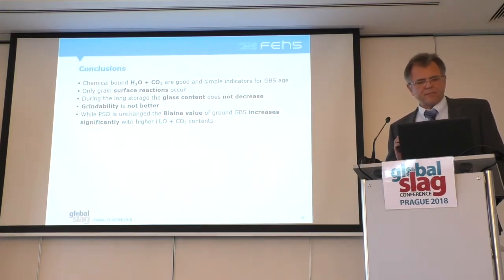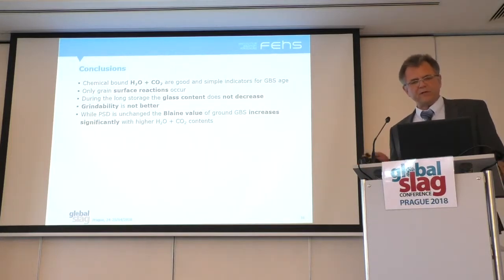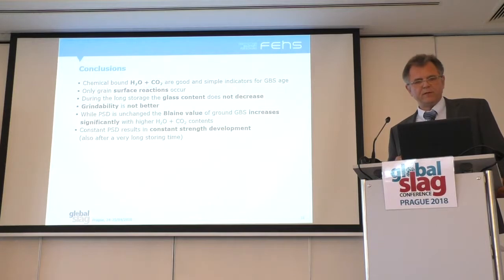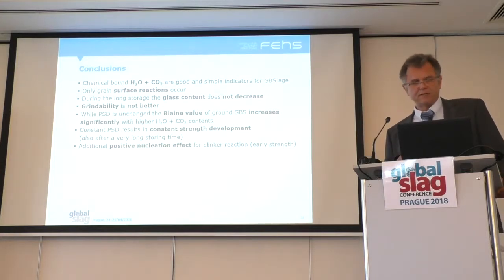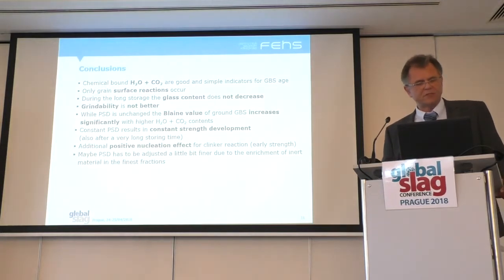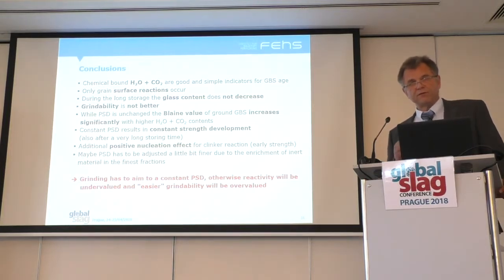And if the PSD is constant, the Blaine value will increase enormously. But the strength development based on constant fineness will be more or less also constant. Maybe there are some positive nucleation effects. You saw a higher 2 days, a little bit higher 2 days strength. And maybe we have to adjust a little bit the PSD in the finer range, but that's not the most important topic. So again, if you grind stored GBS for cementitious purposes, look to the PSD, don't look to the Blaine value, and then you will have a reactive slag, which will be so reactive as glass content and chemistry can offer.